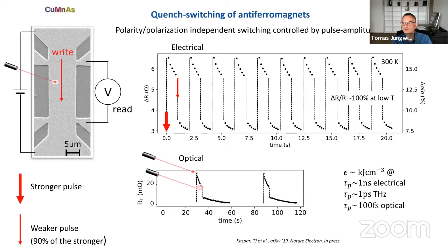Now let's take a look at what type of electrical response we get in this new quench switching regime. So when we talked about the conventional reorientation switching, whether it was in ferromagnets or antiferromagnets, we could control it reversibly by changing the direction or the polarity of the writing current. In the quench switching experiment, the switching is in fact polarity independent. It doesn't depend on the direction of the electrical current, but we can control the switching in a reversible manner by changing the amplitude of the current pulse.